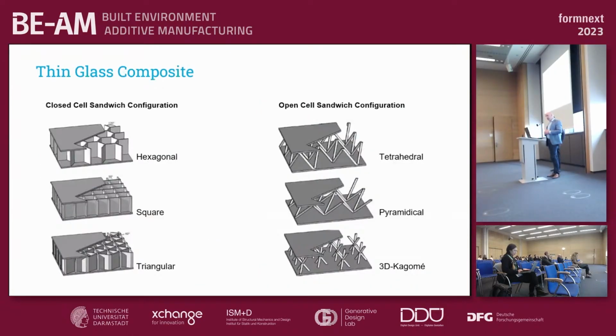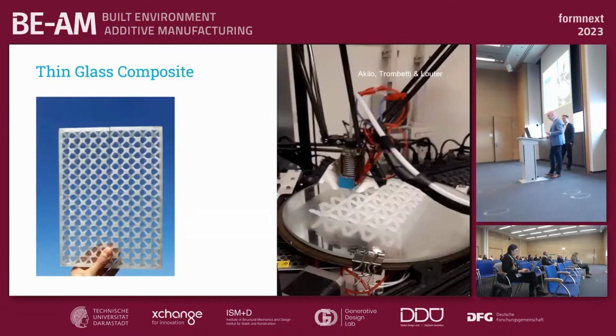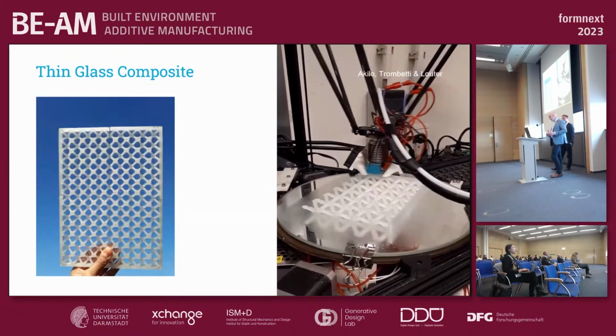But the other concept that we would like to talk about today is more to combine the thin glass with a core pattern to stiffen the glass, because you can imagine that this vibration is too much for a building. It's causing noises, it's causing too much deformation and too much nuisance for building occupants. So we thought about combining it with more conventional, on the left-hand side, closed cell or honeycomb kind of patterns, but also perhaps with open cell configurations. And there the idea came also to print those patterns. And the first student looked into that to print a truss structure.